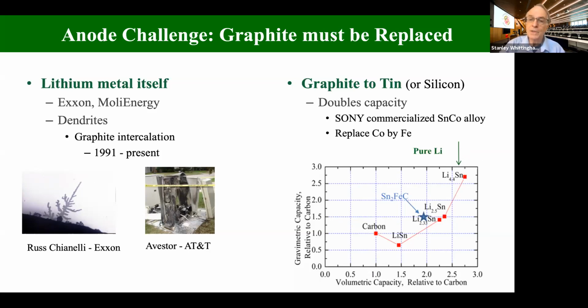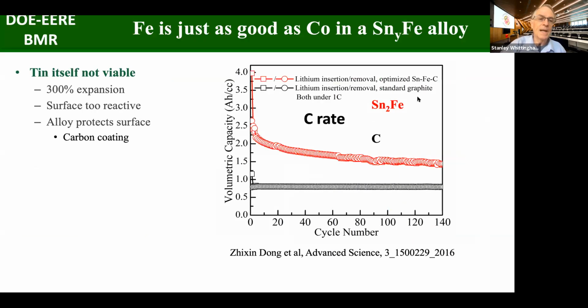Sony, in fact, commercialized in about 2005 what turned out to be a tin cobalt alloy anode. This is in one of the camcorder cells. Clearly not commercially viable, even though they were selling it, I think, for about $100 a battery. So we decided we'd try to replace this with iron. So we made some iron tin compounds. And I think I recounted it to some of the students earlier.